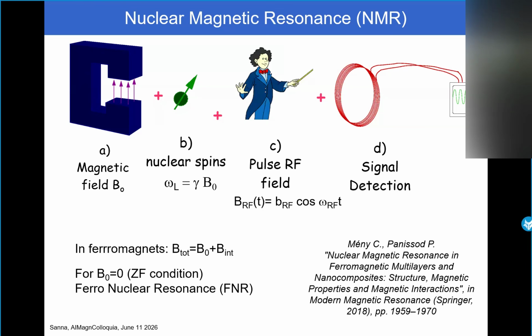In ferromagnets, we can even avoid using the external magnetic field because the polarization of the nuclear spin is already performed by the hyperfine field spontaneously appearing in the material. Okay? And so you can develop a parallel theory, or analogous theory, of this more standard nuclear magnetic resonance by considering the so-called zero field condition, so without any external magnetic field. You can go through this very nice reference about it. This is a less common use of nuclear magnetic resonance.